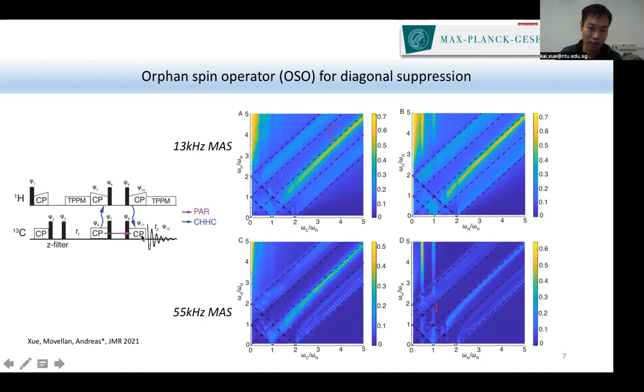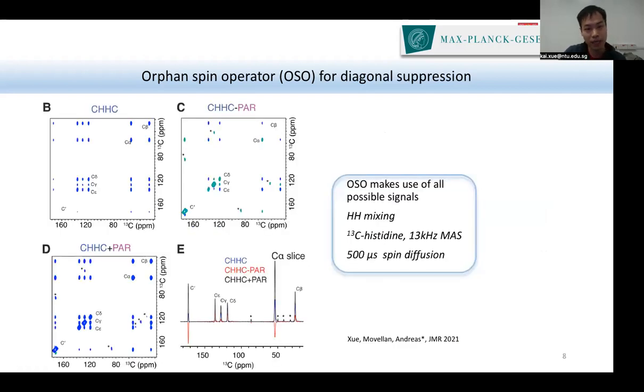The autocorrelation peak is actually a PAR signal, not only autocorrelation, but PAR recoupled. We can make use of it by phase cycling CHC signals minus PAR, and with that we obtain an active diagonal peak. But we can also use it in another way, CHC plus these PAR conditions, and we enhance in general the sensitivity of the experiments. So we can combine in one pulse sequence these two schemes, which is related with the long range, which enables us to extract long range contacts in solid state NMR measurements.